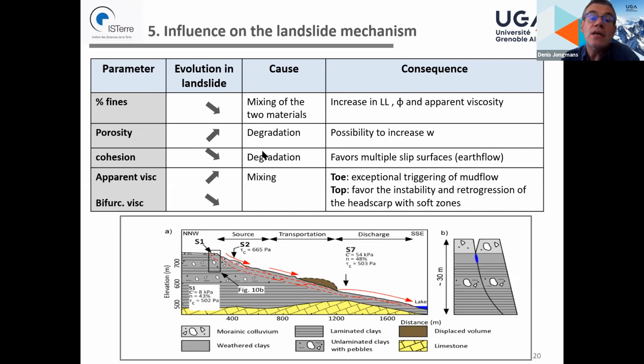The cohesion decreases for the same reasons, for the degradation of the clay. It's our interpretation. Of course, the decrease in cohesion favors the multiple slip surfaces, especially so creating some earth flow. And the apparent viscosity increases in the landslide, probably because, again, of the mixing of the material, while the bifurcation of viscosity decreases, or the thixotropic characteristic decreases inside the landslides. And so the consequence is that at the toe here, we have mainly earth flow. That was what was observed.